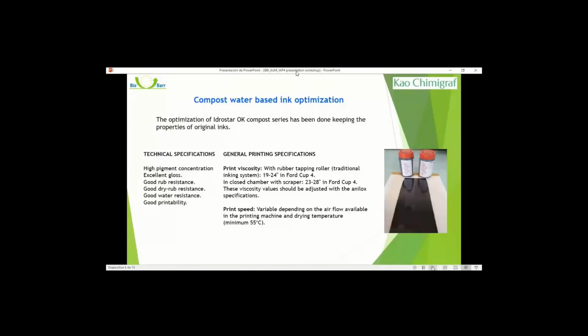After making this change, the Idrostar OK Compost ink series has kept the same features: pigment concentration, gloss, rub resistance, printability, and the conditions to print them remain the same. For the print viscosity, with a rubber taping roller, the traditional inking system, between 19 and 24 seconds in Ford Cup 4, or between 23 and 28 seconds in closed chamber with a scraper or doctor blade. The print speed varies depending on the airflow available in the printing machine and dryer temperature. As general information, the standard speed in flexo machines with water-based inks on plastic film is about 200 meters per minute.